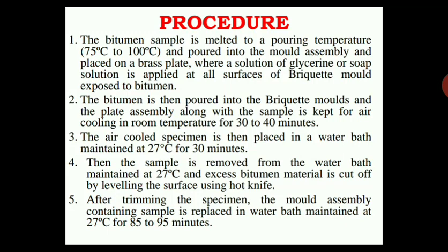Okay, and the air cooled specimen, so after keeping that one in the air cooling system for 30 to 40 minutes, then whatever specimen is available, we need to place in a water bath. The water temperature should be around 27 degrees Celsius, and the time required to keep it in the water bath will be 30 minutes.